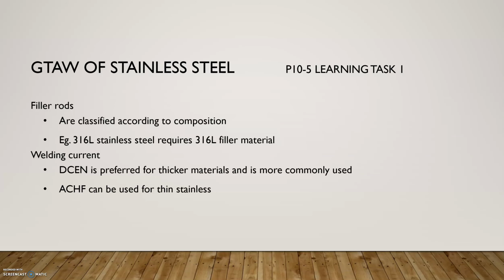Welding stainless steel, filler rods are classified according to composition. For 316 material, you would require a 316 filler rod. DCEN, electrode negative, is most commonly used. And you could use alternating current for very thin stainless, but it's more common just to stick with electrode negative. The introduction of pulsed welding is a good option for welding thin stainlesses on electrode negative with pulse.